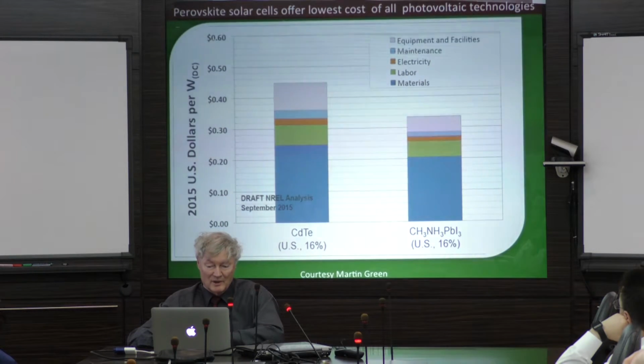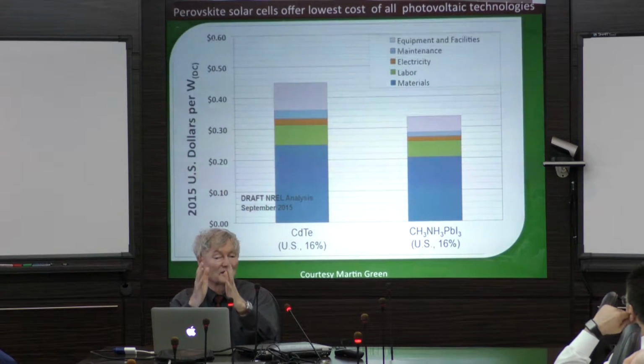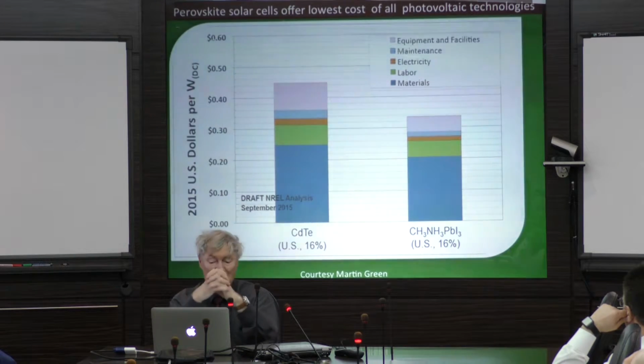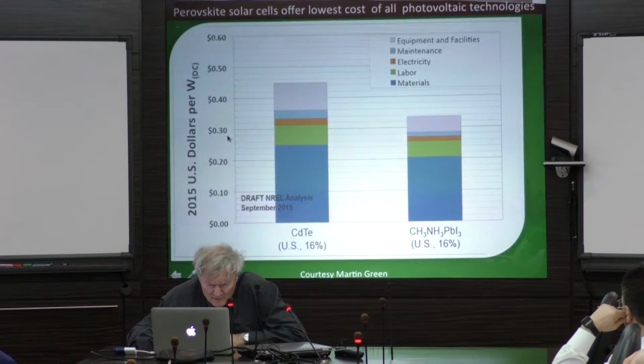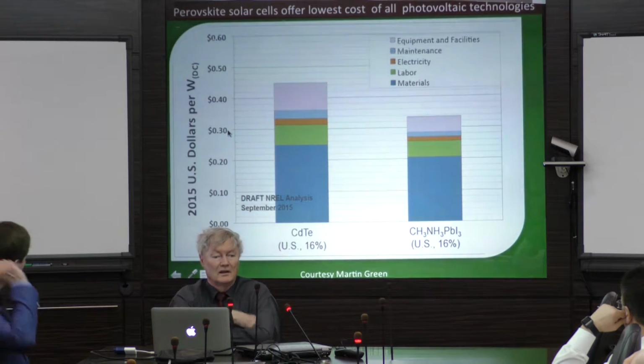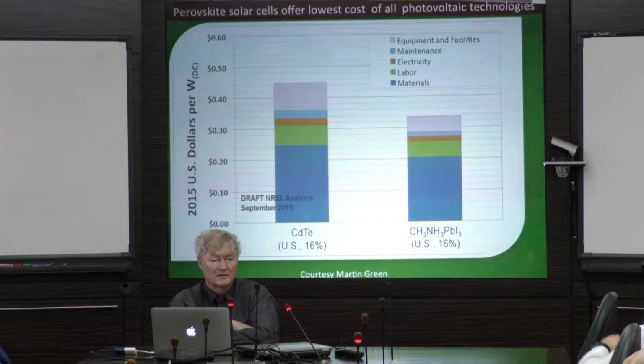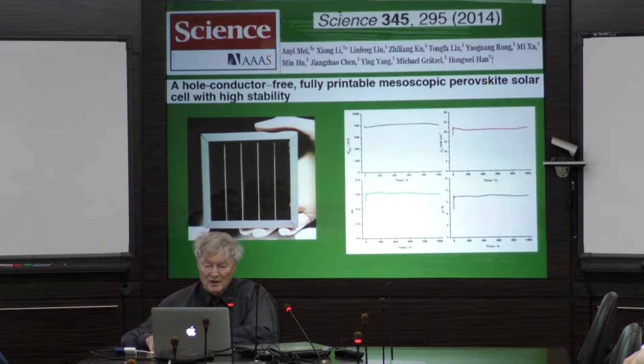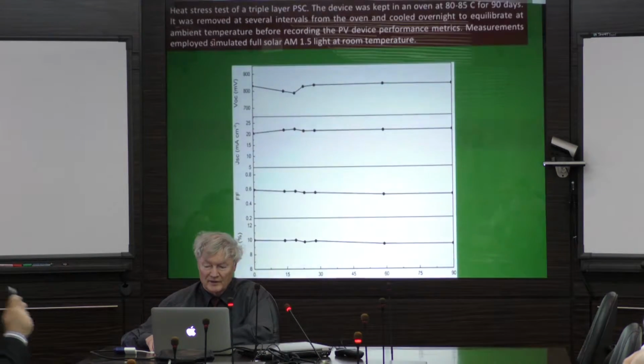So you see the price. I mean, in the perovskite case, the materials, the blue bar, comes mainly from this collector, the hole collector, the organic material that can certainly be exchanged. The perovskite itself would be a negligible cost. So this material cost can come further down. Still, at the moment, we are down to about 20 or 30 cents per peak watt, which would be 2 cents per kilowatt hour if you translate this into electricity price. Also, some stability work has been going on. Make sure these systems are stable.